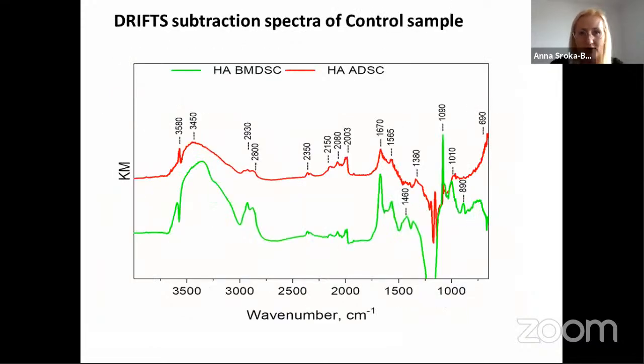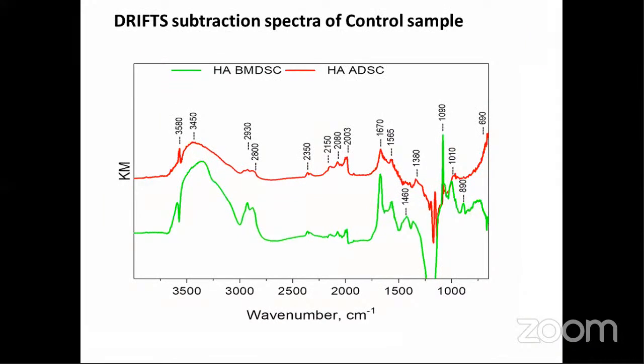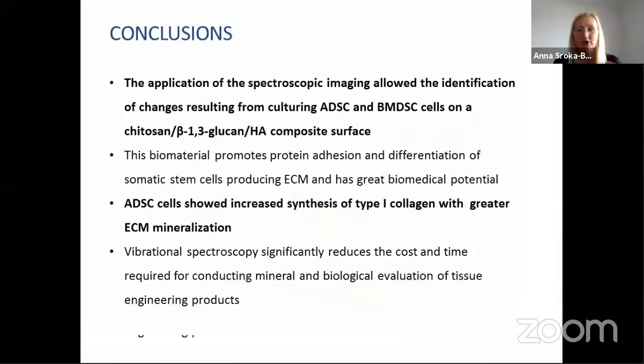And also we notice the different distribution between those two samples. So, going to the conclusion, those different applications of spectroscopic imaging allow us to identify what's going on in the biomaterials seeded with the stem cells, which composite could be visible on the surface, and we can measure the maturity of the collagen.